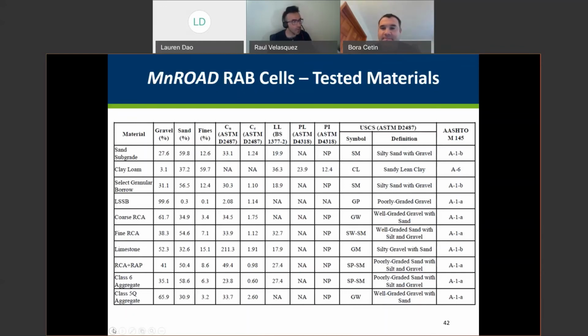Okay. And the next question is, have you noticed white chalky discharge when using RCA as base materials during any part of the research? It was diluted during the hydraulic conductivity test. We see this a little bit, but not at high concentrations. It doesn't look pure white. It has some white chalky, white dust-size fine particles that sometimes come out, but not at high concentrations. So tubing was not clogged. We used the same tubing when we were running the hydraulic conductivity test, and we sometimes see some of the fine particles.